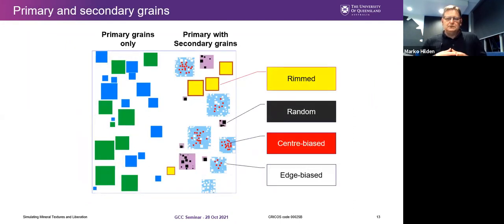Another unique feature of the model is that it can model grains inside grains. So there are what I call primary grains that are surrounded by the matrix mineral, as shown on the left, but secondary grains that are inclusions within the primary grains, as shown on the right-hand side. The model can also control the spatial distribution of the secondary grains. So secondary grains can either be rimmed around a primary mineral, randomly distributed within the primary grains, or biased either to the center or edges of the primary grains. And you can have multiple secondary grains in a given mineral as well.